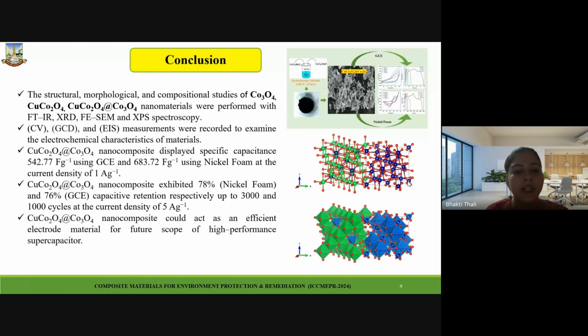With respect to the stability, on nickel foam it was stable up to 3000 cycles, showing a retention of 78%, and on glassy carbon it was 76% up to 1000 cycles at a current density of 5 ampere per gram. So this material could definitely act as an efficient material for future high performance supercapacitors.